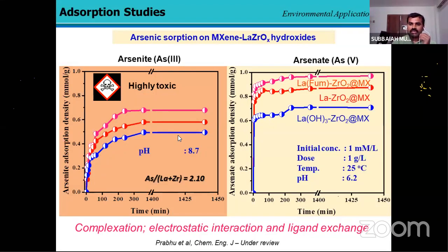That means each lanthanum can adsorb one arsenic, and zirconium can also adsorb, and both lanthanum, oxygen and zirconia can form a bond, lanthanum-oxygen-zirconia, which can adsorb arsenic by a bidentate complex rather than a monodentate complex. This is the most valuable finding for adsorption studies. The mechanism was complexation, electrostatic interaction, and ligand exchange.